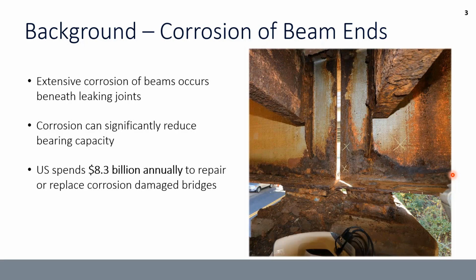So this is the issue we're dealing with. The real issue is shear transfer. The flexural capacity is fine: even if we lose a significant portion of the bottom flange, the bending moments are so low at the end of the beam that it really doesn't affect performance. But shear transfer is the major issue we're dealing with here, and to accommodate the bearing reaction forces and transferring those into the girder.